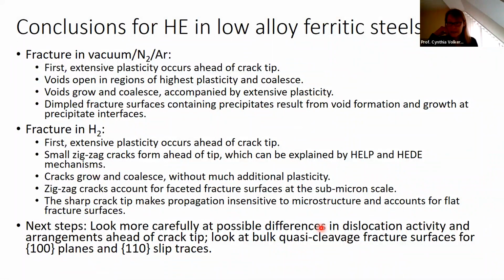But once it's thinned and the stresses are high ahead of the crack tip, we see very, very distinct behavior between the hydrogen case and the non-hydrogen case. In one case, we get holes opening and dimples forming, and in the other case, we get these zigzag cracks, which we think can account for the quasi-cleavage surfaces one finds in bulk materials.